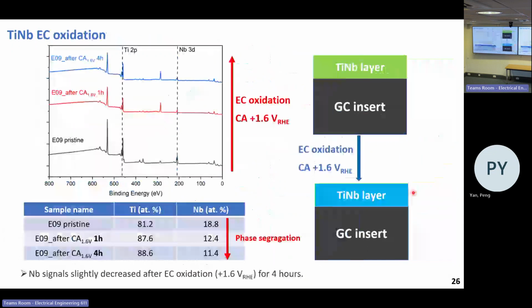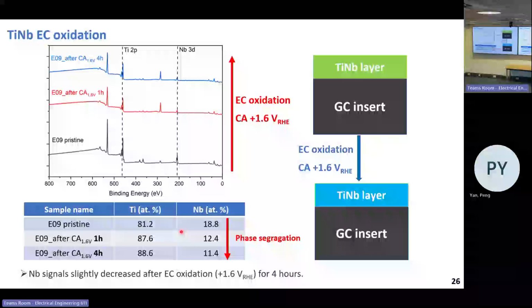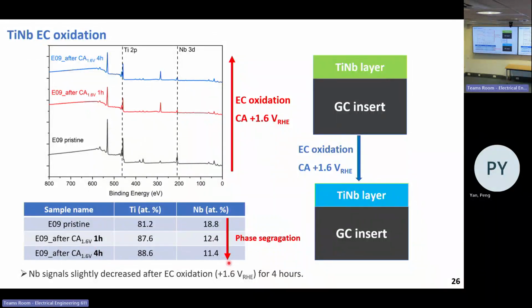With regard to electrochemical oxidation, maybe it could show similar behavior. So we polarized these films at 1.6 versus RHE, and the niobium ratio also slightly decreased after 4 hours of polarization. That also showed it segregated, which could be a problem for titanium niobium alloys.